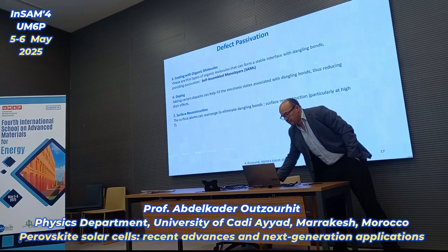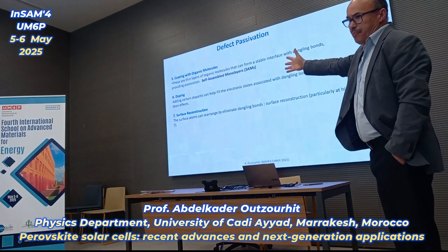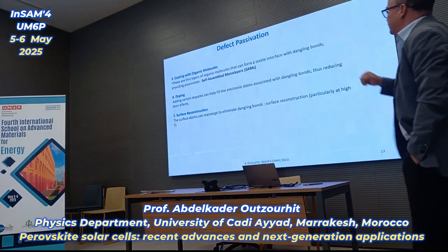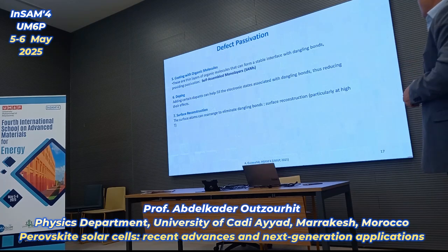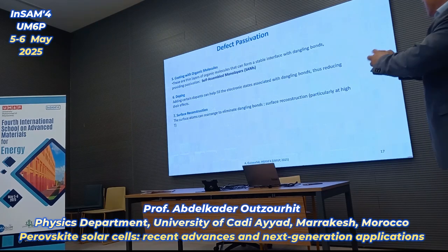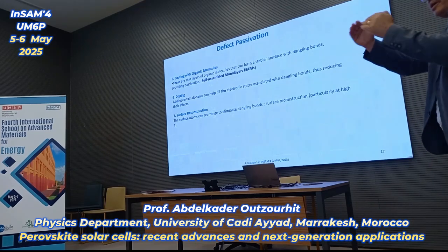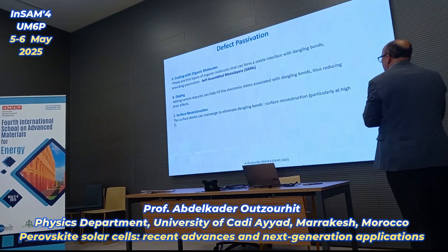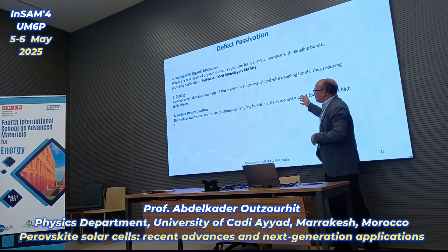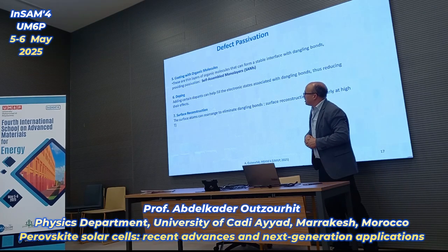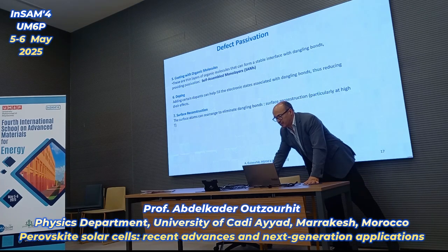You can also coat with organic molecules. Another option is surface reconstruction, where you heat up the semiconductor, and then the bonds at the surface will rearrange, so that you eliminate those dangling bonds. That's what we call a surface reconstruction. And probably Professor Hamid, in his presentation on surface techniques, maybe he will talk about this surface reconstruction.